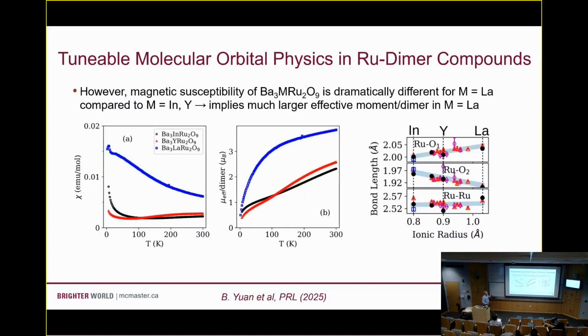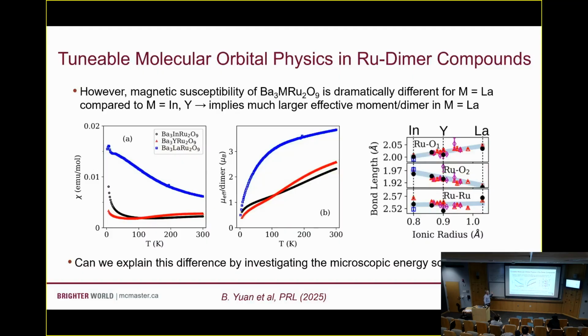So what's interesting is, in spite of the fact that the structure is not changing very much at all, the magnetic properties of the compounds are very different. So in particular, the lanthanum compound here is a huge outlier. Okay? The magnetic susceptibility is much higher, and you can pull out an effective moment per dimer here, and you see that it's somewhere between 2 and 3 times larger across this large temperature range here. Okay? So we have some big anomalous changes to the magnetic properties, and the question is, how can we make sense of this? And is this a problem that we can solve with RIXS?